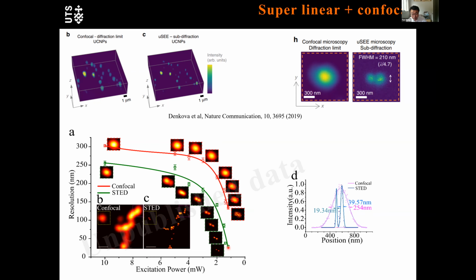You pretty much just decrease the pumping rate. And for this one, actually, you just control the carrier distribution in the top level, and then you pretty much enhance the depletion efficiency. So this is why we have this high resolution here. So we've seen that the two resolutions just synchronize when excitation power goes really low, both of them showing high resolution.